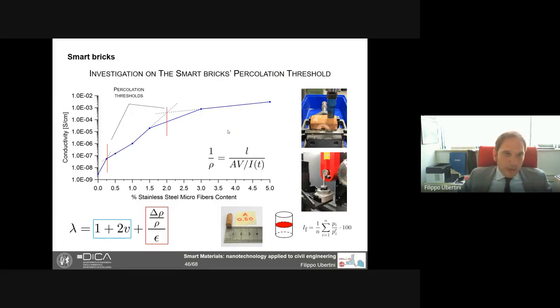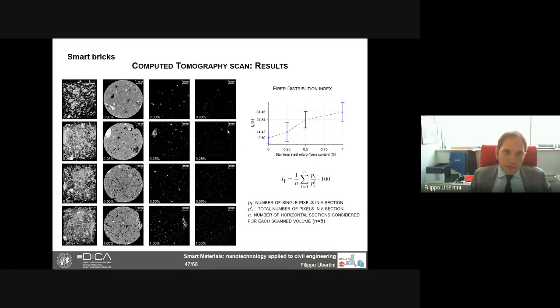And by the way, there is a double percolation because there is a percolation at around 0.25% and another one around 2%. Well, actually, if we look at the microstructure of these materials, for instance, through X-ray tomography, these scans were made at the Technical University of Braunschweig in the framework of a collaboration we have with the group of Professor De Laurentiis. We saw that actually the microstructure is quite complicated. We have microporosity, we have microcracks, we have iron particles and other metals dispersed in the matrix besides the fiber. So this may justify the double percolation, even if it's something we have not yet studied in detail.